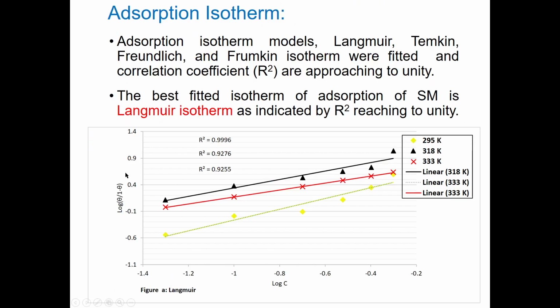We also did the adsorption isotherm study. We used various isotherm models, Langmuir, Temkin, Freundlich, and Frumkin, and we fitted the data on them. We found that the best-fit isotherm of the adsorption for the sweet melon is the Langmuir isotherm, as indicated here with the high value of R square, which shows that it is following the Langmuir isotherm.